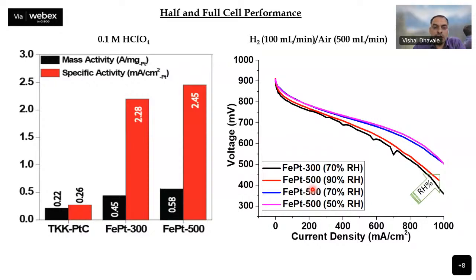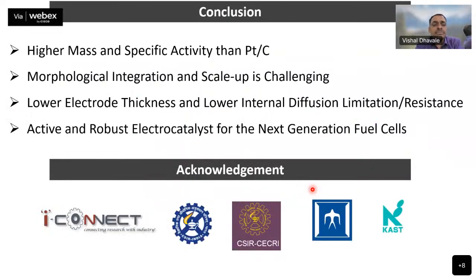So this is the last one, the conclusion. We observed higher mass and specific activity with respect to PtC because of the nanocapsule structure, where we can utilize the inner and outer cavity of the nanocapsules, the number of active centers can be improved, and overall the utilization of the platinum can be improved. The morphological integration and scale up is still a challenge. We are working on it. And the second thing I talked about, the electrode thickness, can reduce the internal diffusion limitations and the resistance and other things.